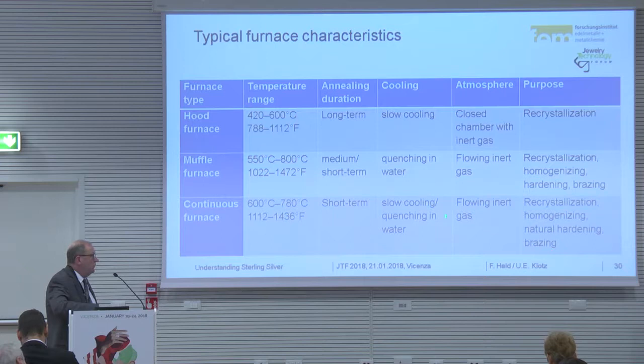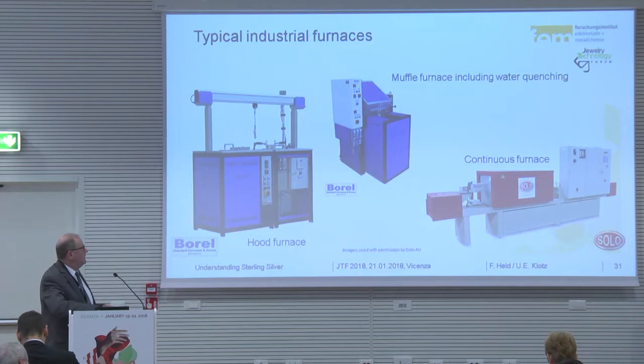This annealing is also called bright annealing, because there is no oxidation. Here you see the furnaces for the different annealings. That's a hood oven you use for large batches, so you need a long time to heat it up, and that's the long-term annealing. The muffle furnace has a shorter time, up to 30 minutes. We can quench in water here, or we have the continuous furnace. You only have a thin sheet or so that you anneal here, and in a few minutes the annealing is done.